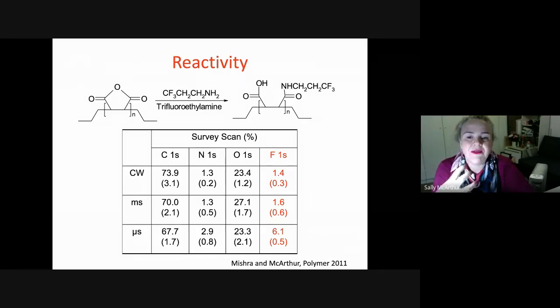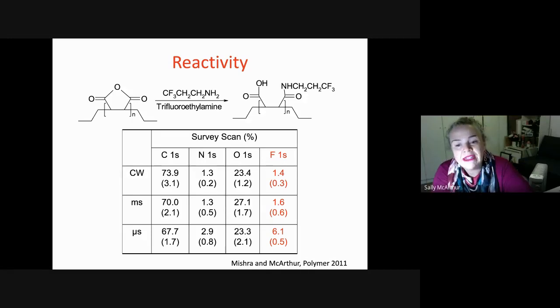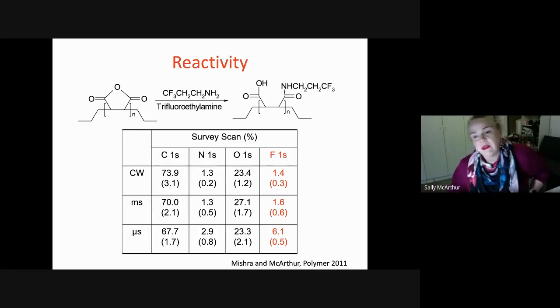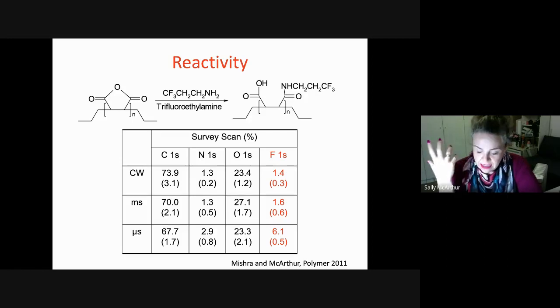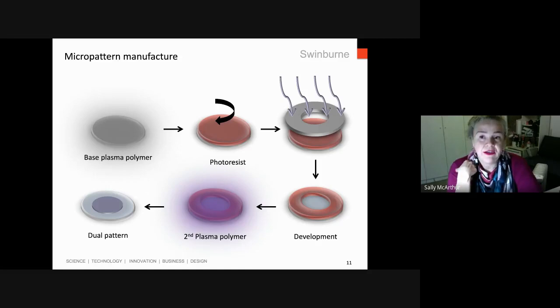And you can see clearly here that we introduce more fluorine as we get up to the microsecond regime. Even though the millisecond data looked like it was introducing more oxygen and more anhydride groups to the surface, they're not reactive. That suggests that they're more ester groups on the surface rather than anhydrides, due to that ring opening and reorganization that occurs in the plasma process. But once we get to the microsecond regime, you can see we can start to introduce quite significant levels of fluorine into the surface, and that suggests to us that we've got reactive anhydrides on that surface, which is all great. But obviously, we have other techniques we can use as well.